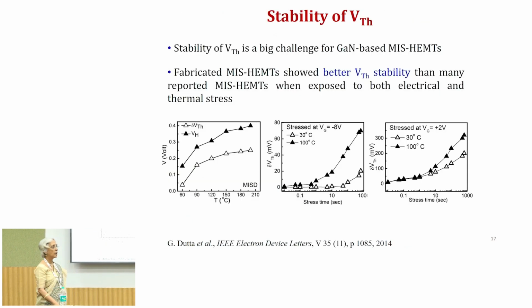And we did a lot of reliability study, because whenever we are depending on charge engineering on threshold voltage, the first question is how stable is this threshold voltage. So, we did a lot of stability analysis, and we found that both for temperature stress and for voltage stress, the variation in the threshold voltage, the change in the threshold voltage is within acceptable limit. So, the fabricated devices showed better threshold voltage stability than many other reported MISHEMTs.